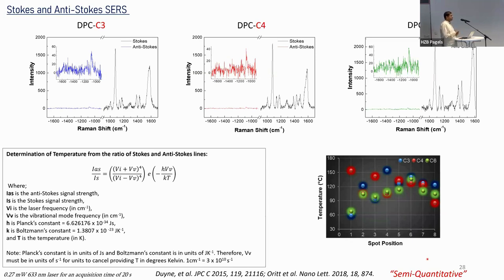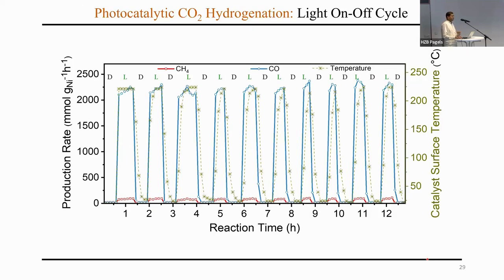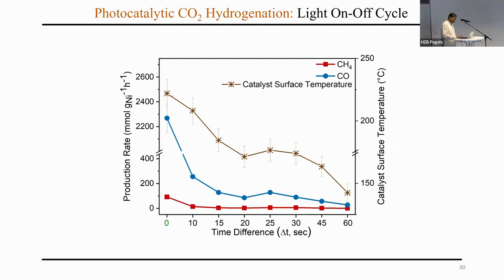Then, coming back to the same question, how do I answer this question? So what we did then was carry out one hypothetical experiment, assuming that our temperature measurement is not accurate and the surface temperature is, say, 1000 degrees Celsius, which is ideally impossible because at 1000 degrees Celsius my gold and everything will melt. But still, just to satisfy the other side, we said, okay, it's 1000 degrees Celsius, and we did one experiment. So at this point, assuming that it's 1000 degrees Celsius and not what we measure, which is around 223, 225 degrees Celsius, when light was on, hypothetically you reached 1000 degrees Celsius, and I switched off the light.